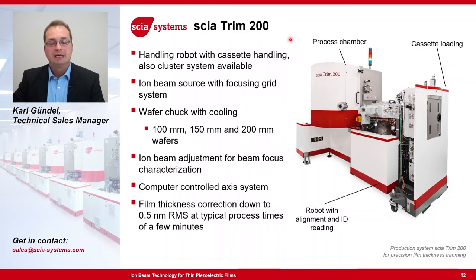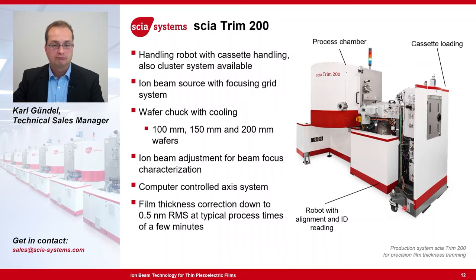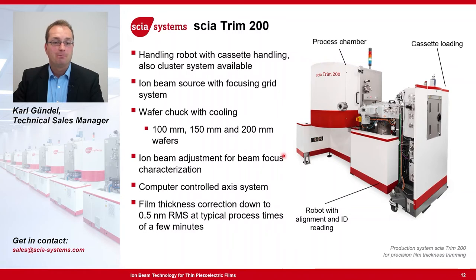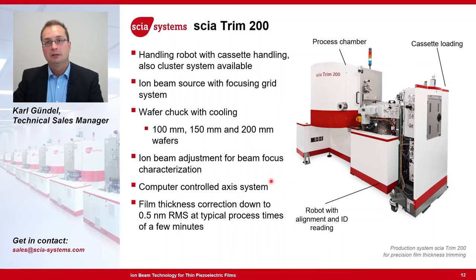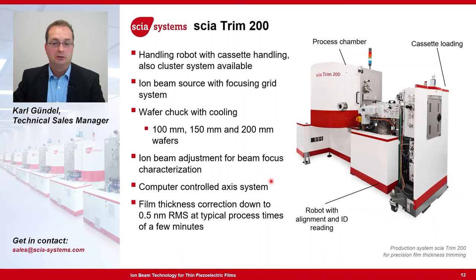The scia Trim 200 is used for this optimization of piezoelectric films. This system is equipped with a central handling robot system enabling high volume production. The wafer chuck can be adapted to 100, 150, and 200 millimeter wafers. The computer-controlled axis system enables dwell time regulation of the ion beam in front of the substrate surface. In general, an optimization down to a uniformity of 0.5 nanometer RMS is possible with this system.